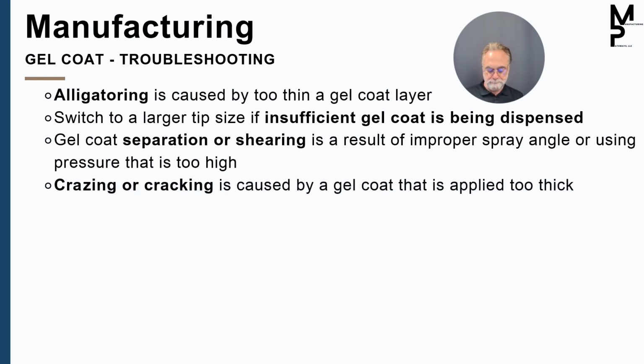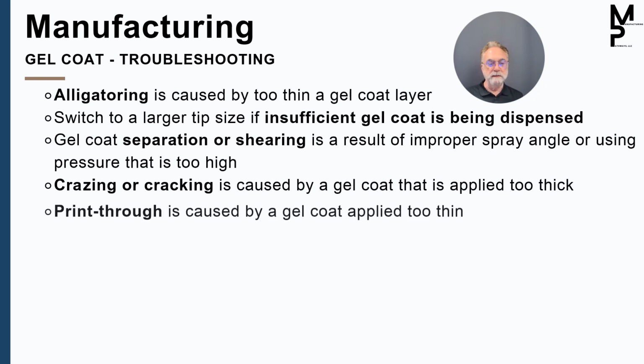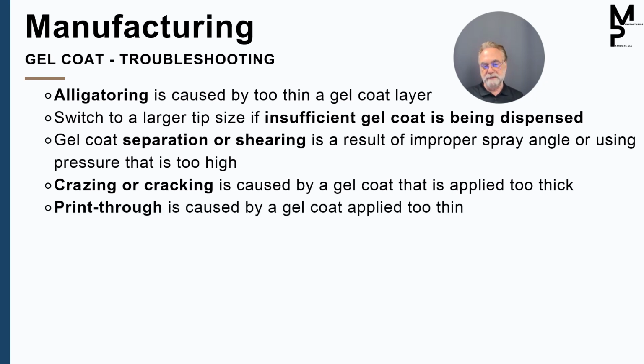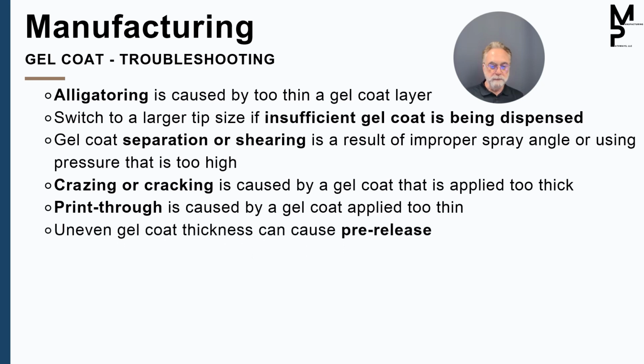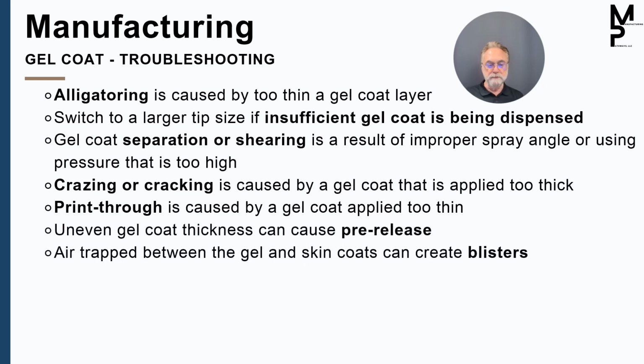Okay, we talked about gel coat being too thick. You can get cracking. Print through is when I see the pattern of the chop strand mat through the gel coat. The gel coat should be thick enough that when I put the first layer on, the skin coat, which is coming up next, I shouldn't see that pattern in the fiberglass. If I see it, it's either the gel coat wasn't cured properly or the gel coat's too thin. Okay, uneven gel coat causing pre-release.